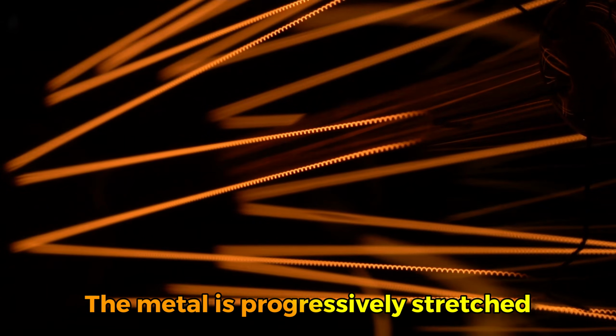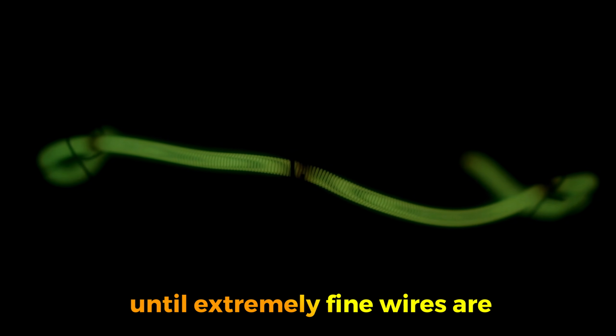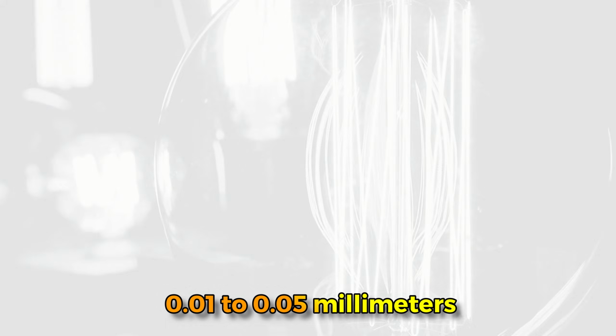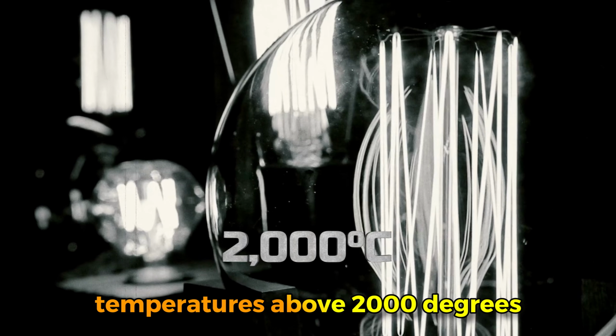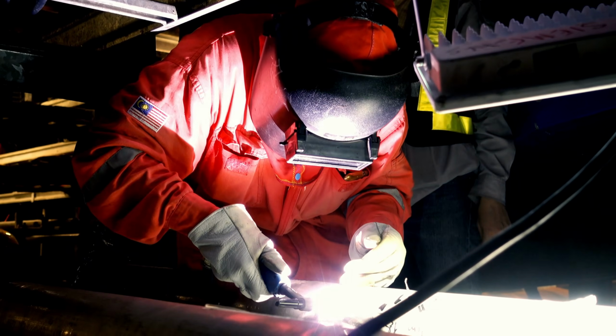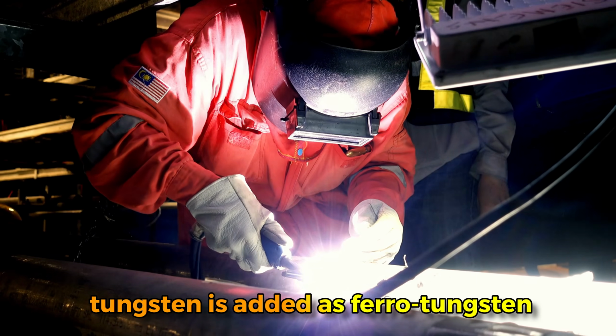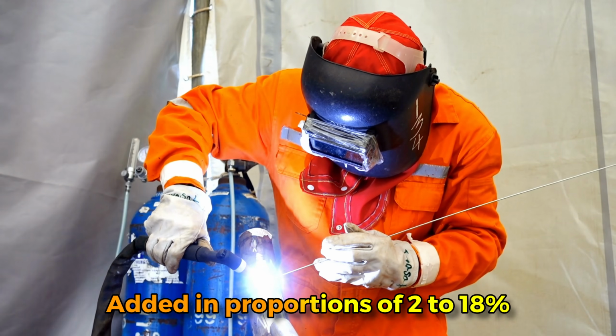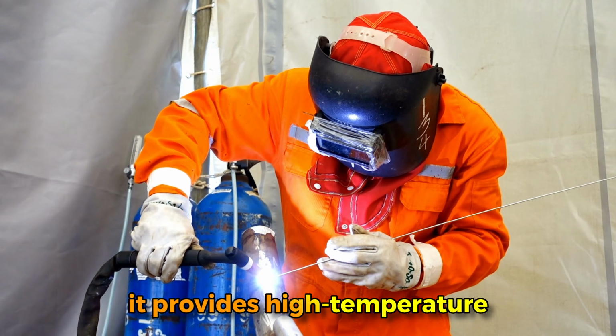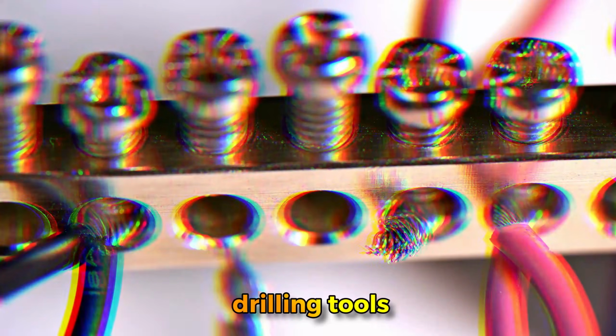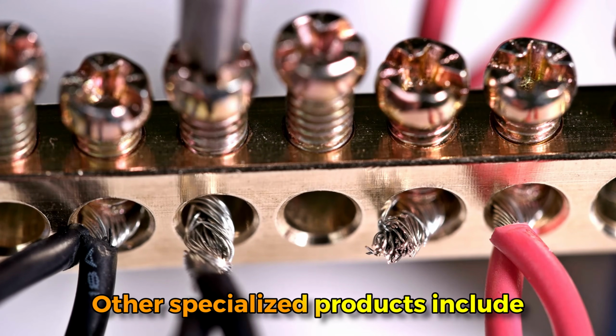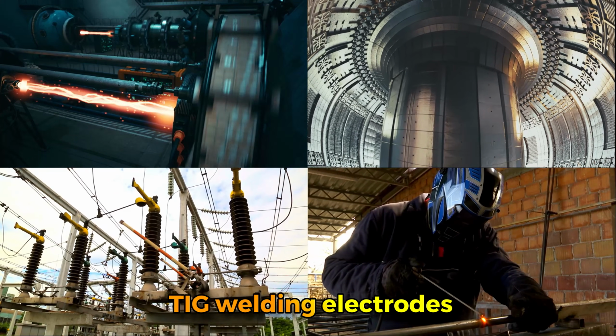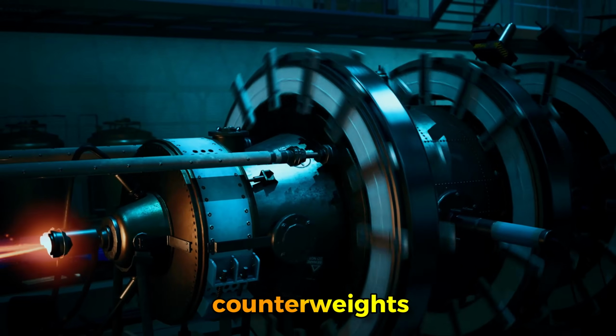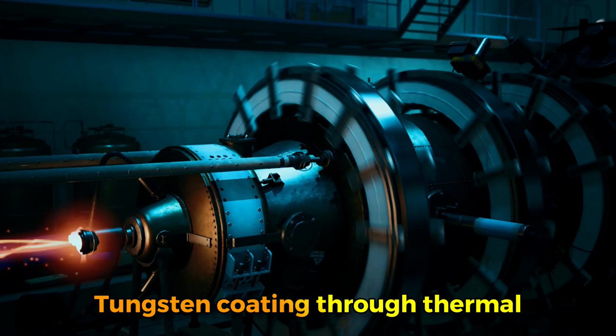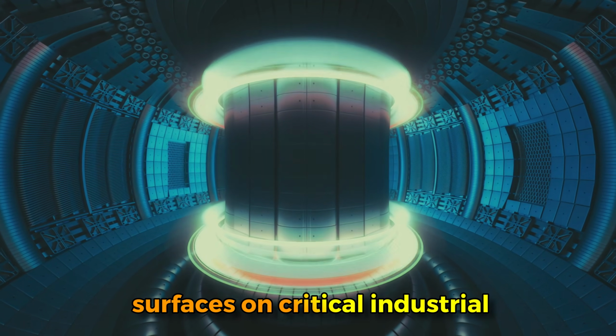Filaments for lighting and electronics are produced through tungsten wire drawing. The metal is progressively stretched through dies of decreasing diameter until extremely fine wires are obtained, 0.01 to 0.05 millimeters. These filaments can withstand temperatures above 2000 degrees Celsius without melting. For alloys, tungsten is added as ferrotungsten or metallic powder to steels and superalloys. Added in proportions of 2 to 18%, it provides high temperature resistance, hardness, and wear resistance. The resulting alloys are used in aerospace turbines, drilling tools, and military armor. Other specialized products include electrical contacts, TIG welding electrodes, nuclear reactor components, counterweights, and radiation shields. Tungsten coating through thermal spraying provides wear-resistant surfaces on critical industrial components.